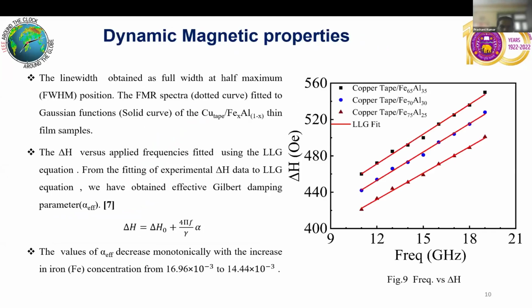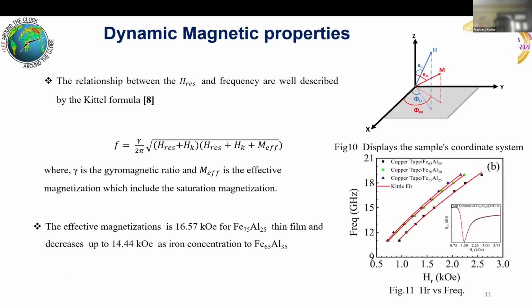This is the dynamic characteristics we have measured using the vector network analyzer, and when we plotted it and fitted it with the LLG equation, we find that the Gilbert damping decreases with increase in the iron concentration. This is because with increase in the iron concentration, structural defects decrease and magnetic ordering increases. This basically gives the data of the magnetization.